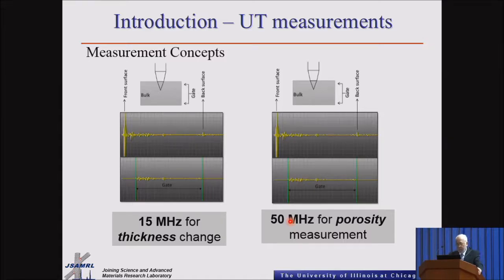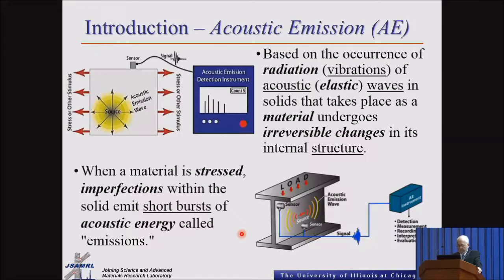Now, of course, the defects come in different sizes. So one of the parameters that you have to adjust has to do with the frequency. In terms of thickness, usually if people want to measure thickness, they use a frequency in the range of about 15 megahertz. Now, for porosity, when you're talking about very small porosity, then you have to increase the frequency so you can decrease the wavelength, and be able to detect the porosity.